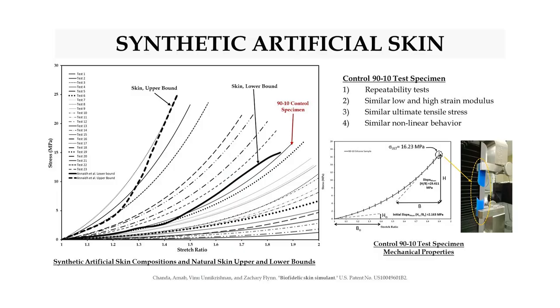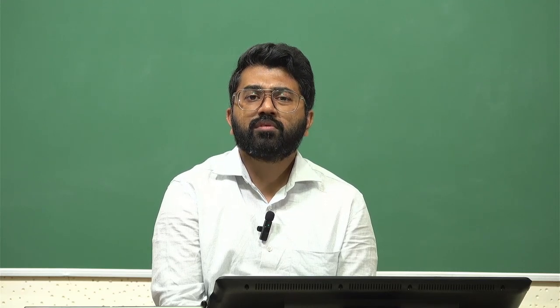Third was ultimate tensile stress. What is the maximum limit to which you can pull this, or the maximum amount of load which you can apply to this skin specimen before it completely fractures or ruptures? Can we compare that with real skin properties, right? What we did see here on the figure on the right is a certain fracture pattern, and the silicone based specimen did fracture. But what we did notice was this fracture pattern was very, very different from how real skin would fracture, right? So, that means it is not a very reliable metric to study ultimate tensile stress properties, and also the ultimate tensile stress values were way different. They were within certain ranges, but they were still very different.